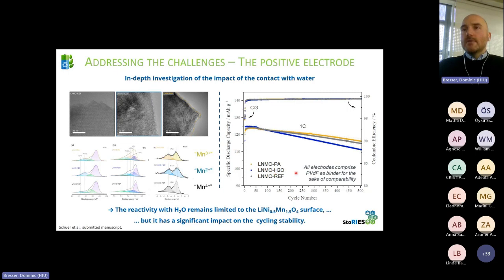And the material that got in contact with water before then being processed the same way as the reference shows a greater fading. So I need to highlight that. I mean, this is, let's say, rather large resolution, right? So we're talking here about the difference after 500 cycles of maybe 5 milliampere hours per gram. So that's not substantial maybe, but it's still significant. And we can prevent this nicely by adding this phosphoric acid, as you can see here in yellow, right? Which is even outperforming the reference material.